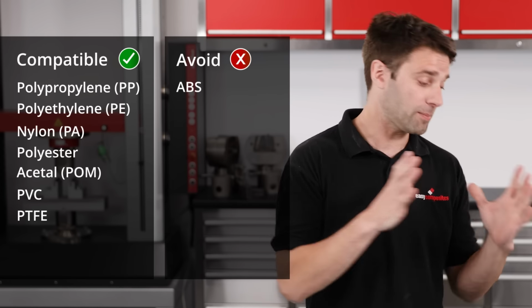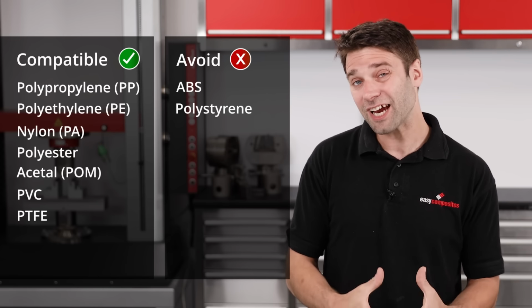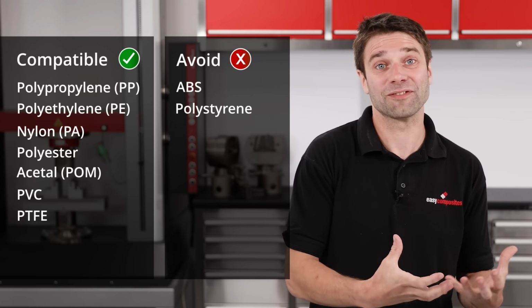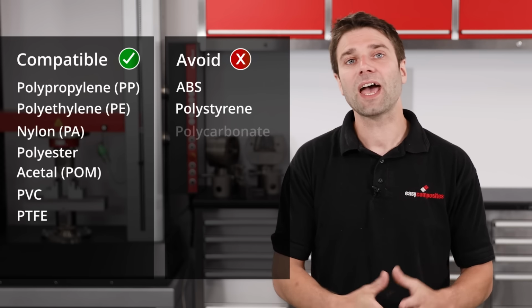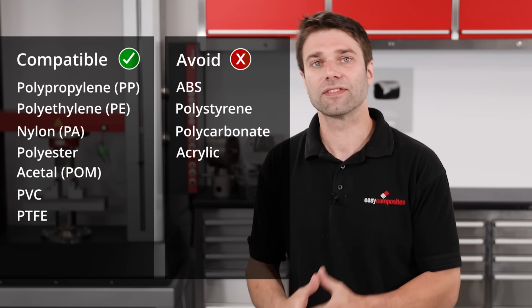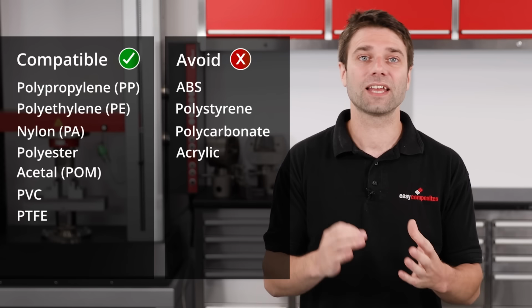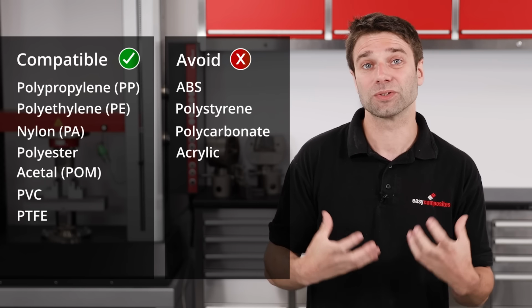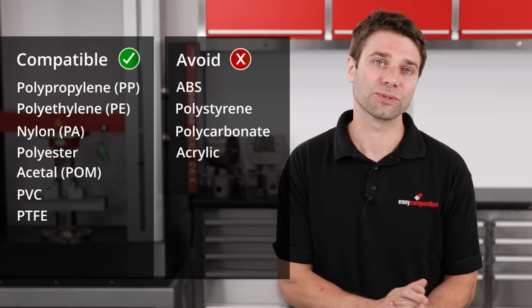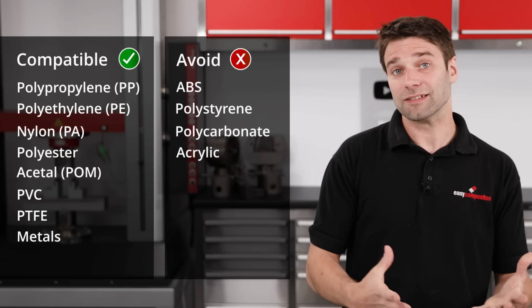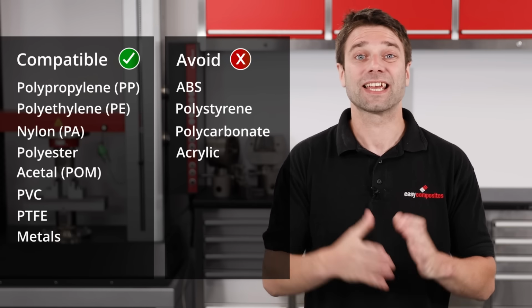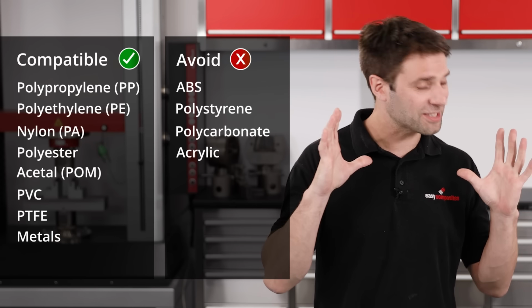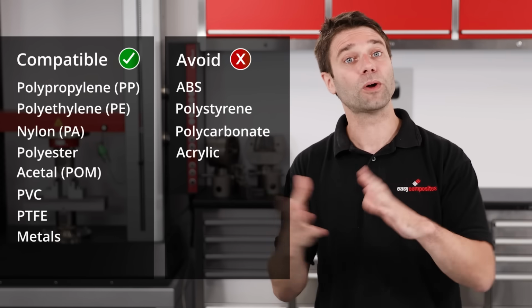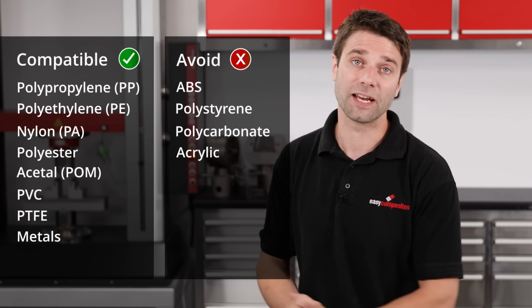There are also some other plastics that don't release well. The plastics that I would avoid are ABS, as we've just discussed, polystyrene, as that dissolves with the styrene in the resin in just the same way, and then we have polycarbonate and acrylic. These, although less affected, can experience some level of etch when exposed to solvents, and so I would avoid those too. Then we've got metals. Any bare metal surfaces can be used as a pattern, so pulling moulds directly from things like engine covers or folded metal profiles is going to be fine.